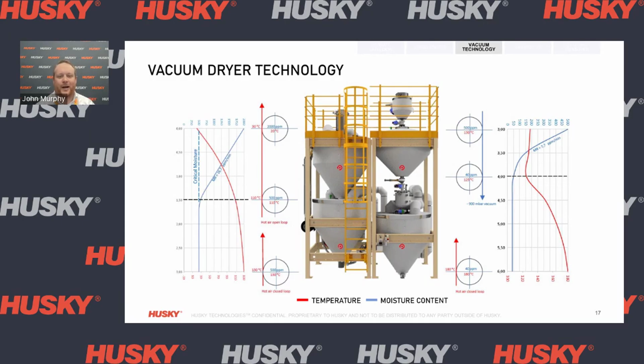When we look at the vacuum drying system, we can see that there's a lot more going on the screen here, but I'm going to walk you through each of the phases so you can understand what's exactly happening within each phase. So we will start off on the top left-hand side of the screen, which is stage 1, the preheating hopper. We're starting off at the same conditions at room temperature, or 20 degrees Celsius, with a humidity level of 2000 ppm moisture within the pellets.